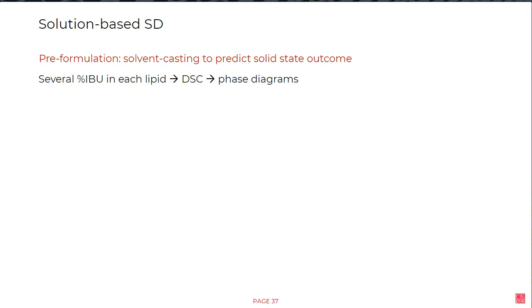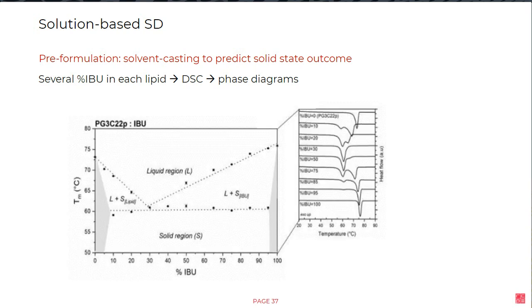So basically, we prepare solutions containing ibuprofen and one lipid, with ibuprofen in different percentages with respect to the lipid. Then the solvent was evaporated and the remaining solid is analyzed by a DSC. I'll show you here one example of these findings for PG3, one of the PGFAs that I showed you, in combination with ibuprofen. So in the x-axis, we can see the percentage of ibuprofen in relation with the lipids, and in the y-axis, we can see the melting temperature.